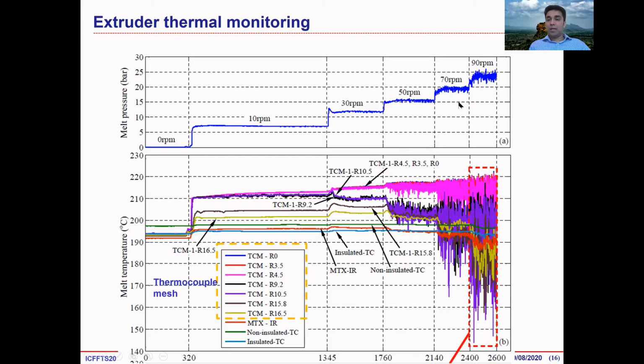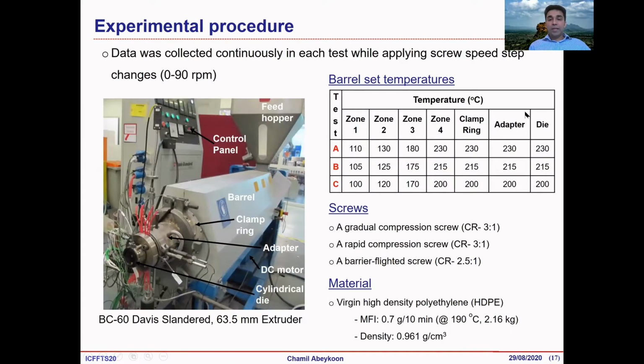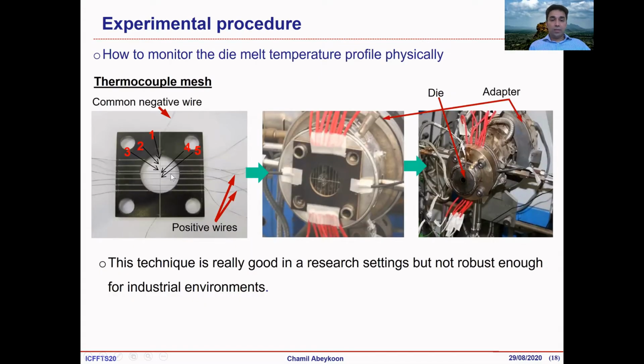Then we developed some experimental setup. This is what we call the thermocouple mesh that we developed. We place that across the melt flow. This is a mesh, and I'll show you in the next slide. In here, you'll find we can place several junctions across the melt flow. Each and every junction will develop a voltage, and that voltage can be converted to a temperature value using an algorithm. Therefore, we can get the temperature profile across the melt flow.